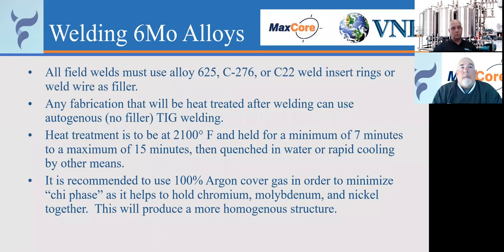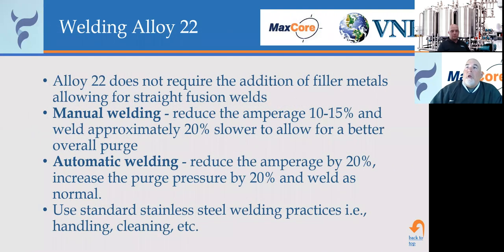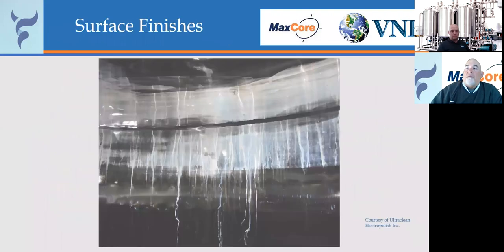So when you're talking about doing welds in 6 moly alloys, now I'm starting to run out of time, aren't I? Mm-hmm. So basically you want to over alloy fill welds by using a weld insert ring. If you can't use a weld insert ring, then you can also use a weld wire. You don't have to use a weld insert ring. A weld wire works just as well as a weld insert ring. We won't get into the heat treatment and so forth. We're going to skip past this because we're running out of time. We don't have time to get into surface finishes. We can do this another time if you want to.